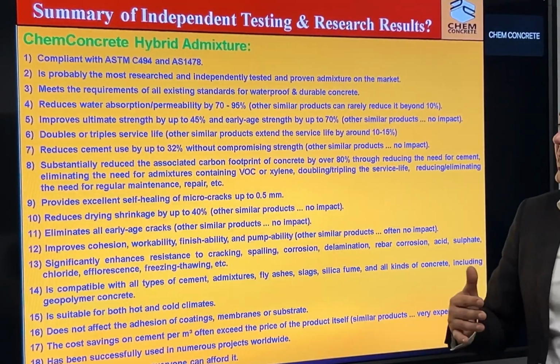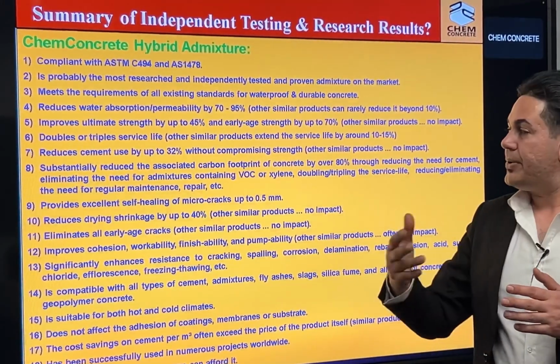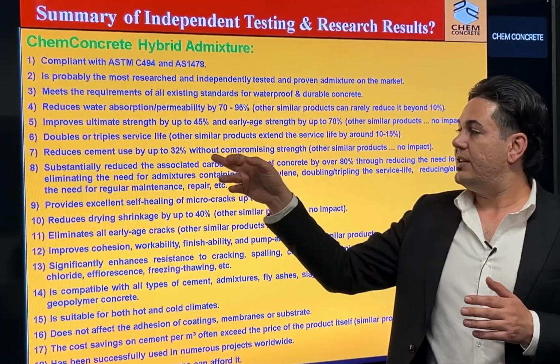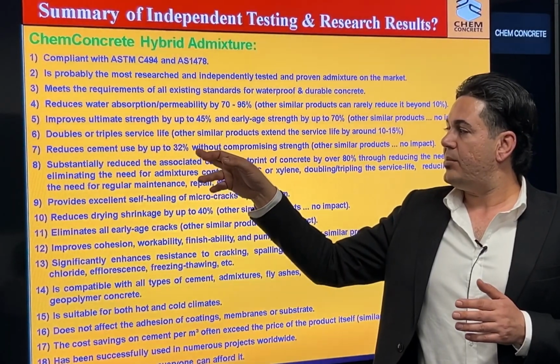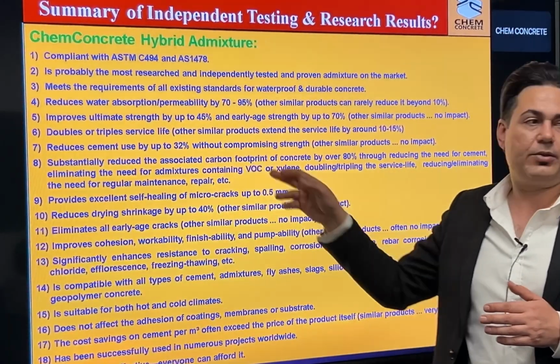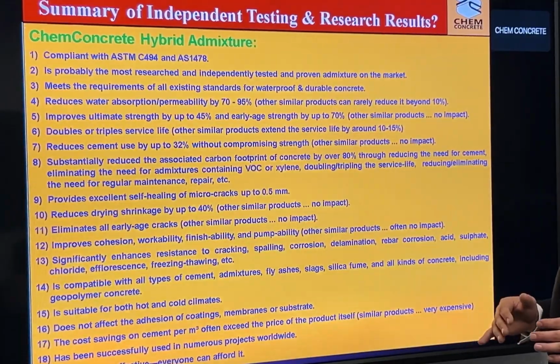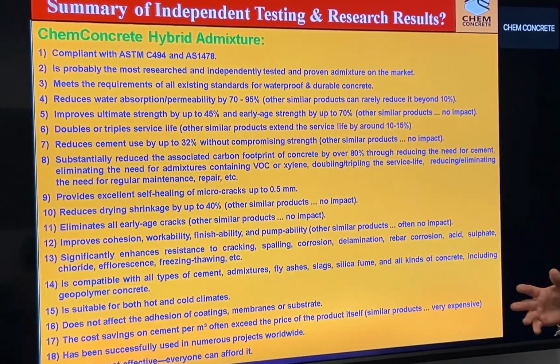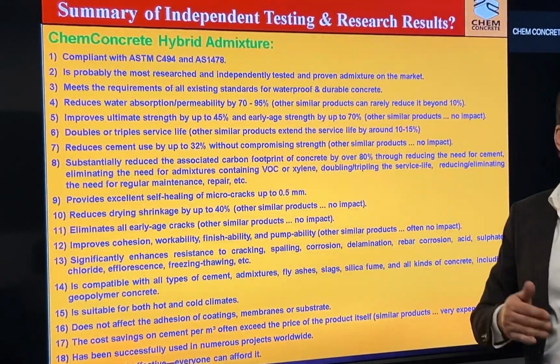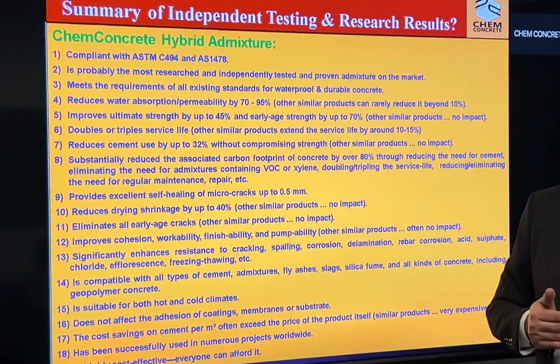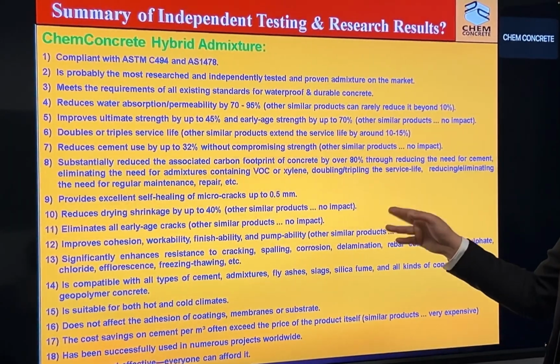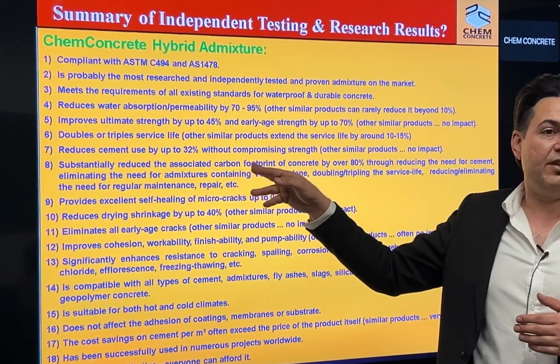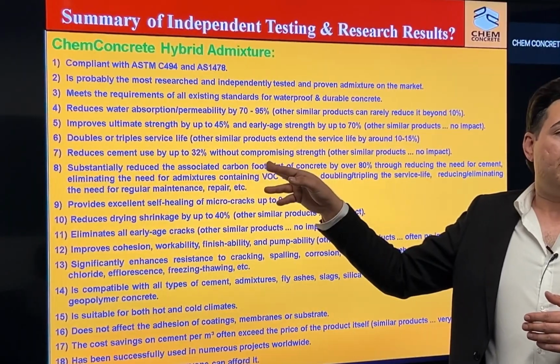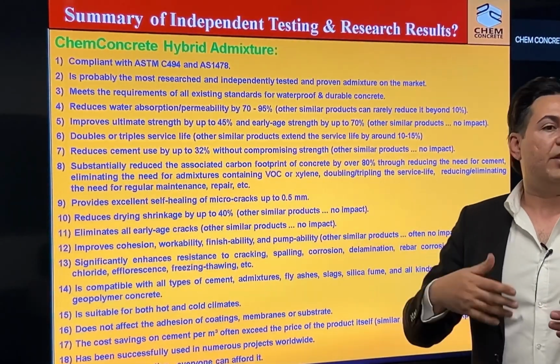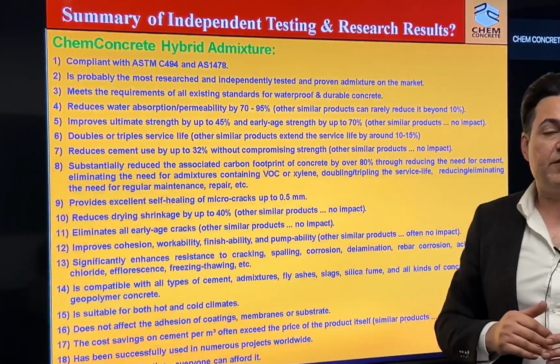And then another significant advantage is that our product, because of significantly increasing the strength properties, allows reducing the amount of cement by up to 32% without compromising the strength. But typically other products don't provide such an opportunity to reduce the amount of cement by up to 32%. And in most cases, the cost saving from cement is higher than the price of the product itself.